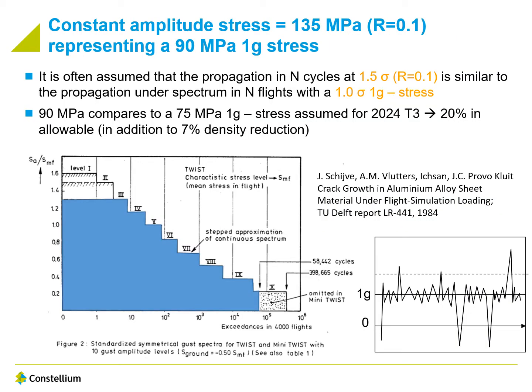There was an initial question about what would be the appropriate loading of the panel. We selected the constant amplitude loading at 135 MPa maximum stress. That is representing a 1G stress of 90 megapascal. This is a factor of 1.5 between the 1G stress and the constant amplitude stress. One cycle at R equals 0.1 represents one flight with a 1G stress of 90 megapascal. This is typical from the literature.